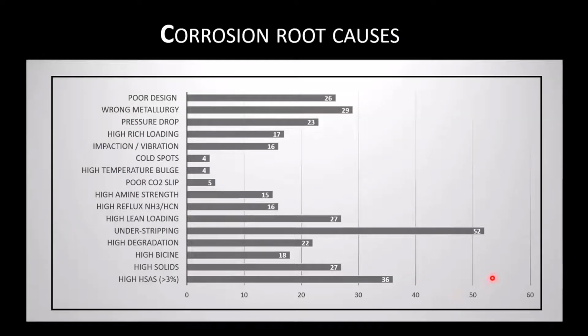So what did our root causes say? The highest one of all was understripping, and also high lean loading. So 52 and 27, that's almost 80 of the total root causes were related to failure to properly regenerate the solvent. We cannot be leaving high H2S in the amine that goes down to the reboiler and in our lean piping, because a lot of that lean piping is hot. We have to remember that corrosion is a chemical reaction, and all chemical reactions proceed faster and more aggressively at high temperature. So whenever we've got acid gas and high temperature in the same place, we're just asking for trouble.